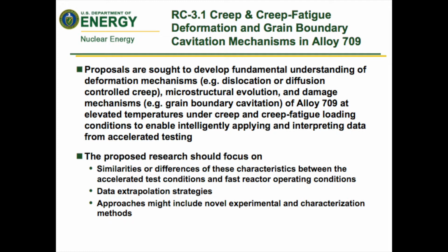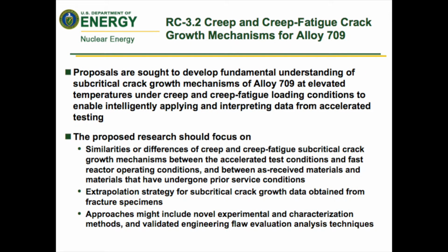extrapolation. The research should focus on both the similarities and differences of the characteristics between the accelerated test conditions and the actual operating conditions of the reactors. Come up with strategies for data extrapolation. And I might add, you get extra points if you can come up with approaches that include novel experimental and or characterization methods. The second category deals with creep and creep fatigue growth mechanisms, crack growth mechanisms for 709, and